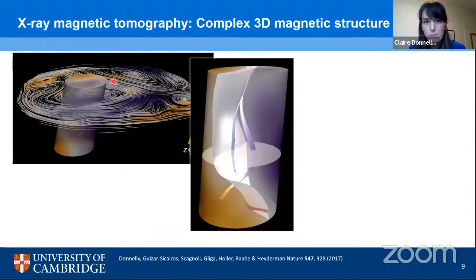Now, when we look at this in a bit more detail, we can notice a few different things. First of all, the color that indicates the vertical component of the magnetization. On the left-hand side, the magnetization generally points up. On the right-hand side, it generally points down. And in between, we have this white surface, which corresponds to the magnetic domain wall. Now, what is really interesting is that within this subvolume, our vortex core, indicated by this isosurface, actually crosses the domain wall at two points, here and here.